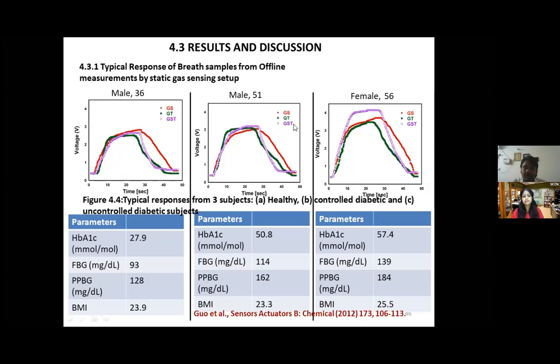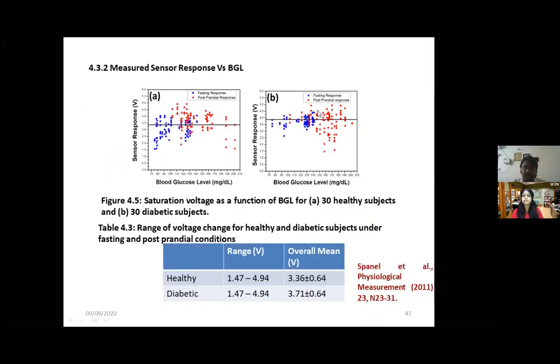To identify these differences clearly, we took the saturation voltage of the three sensors and plotted separately for healthy and diabetic patients, fasting and postprandial, both conditions. The average response of all these sensors is 1.1 times, that is 10% higher for diabetic subjects compared to healthy subjects. This is very minimal, 10% for 60 subjects, but we are further working on it to improve this. There is a definite increase.